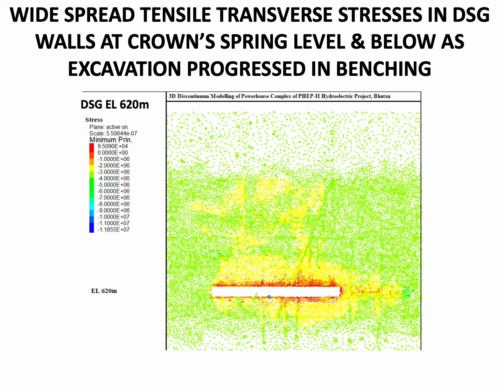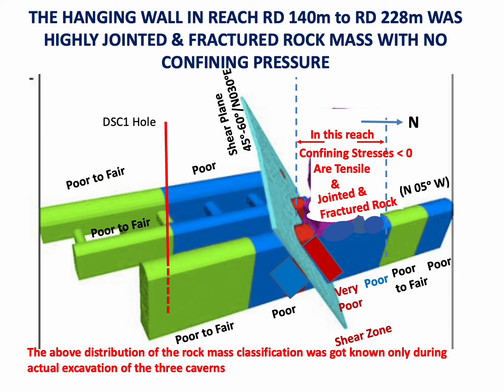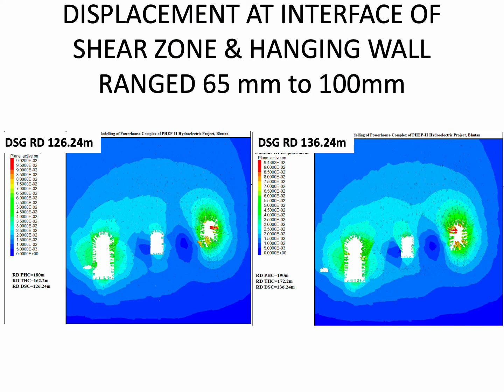In the plan we see all along the length of the downstream surge gallery, the transverse direction minimum principal stresses are tensile. So the hanging wall in the reach 140 meter RD to 228 meter RD, which was highly jointed and fractured rock mass, was having no confining pressure present. So in this reach there was no confining pressure available to form the arch action in the crown. Displacements at the interface of the shear zone and hanging wall were ranging from 65 mm to 100 mm.